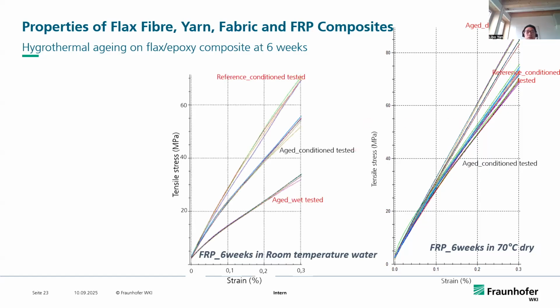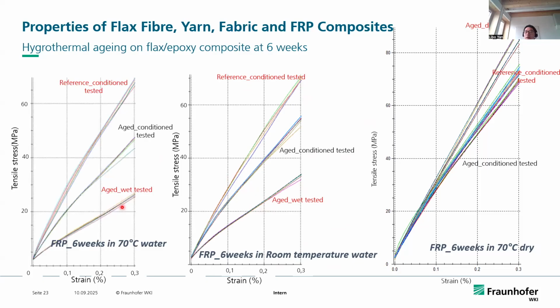Let's move on to take a look at flax FRP composites exposed to water at room temperature for 6 weeks. You can see that compared with the reference samples, there was a significant drop in the tensile strength. Let us take a look at how the flax FRP composites behave in 70-degree Celsius water for 6 weeks. Compared with the reference samples, there was a further reduction in the tensile strength.